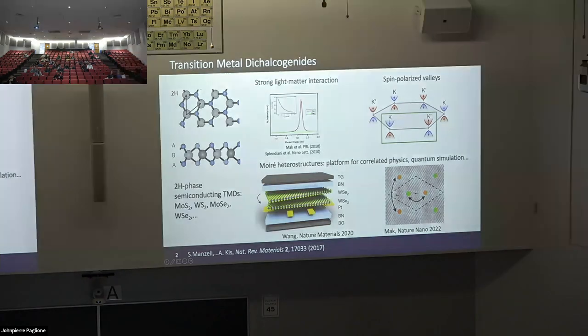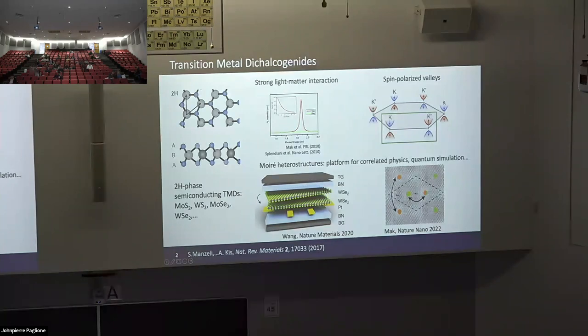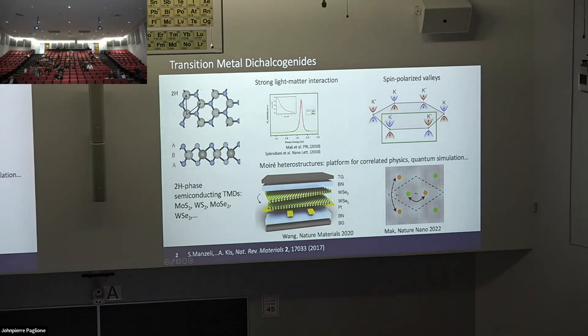We're all excited about 2D materials, and one of the big classes is transition metal dichalcogenides — MoS2, the sulfides, selenides, and tellurides are the main versions but there are many others. They're interesting for many reasons: they have very strong light-matter interactions, so monolayers have a very strong excitonic resonance with strong absorption and photoluminescence. They have interesting spin texture — all the electrons live in valleys at the K point, like gapped graphene where the valleys are spin-polarized, so K valleys have spin-up and spin-down, and K-prime the reverse.